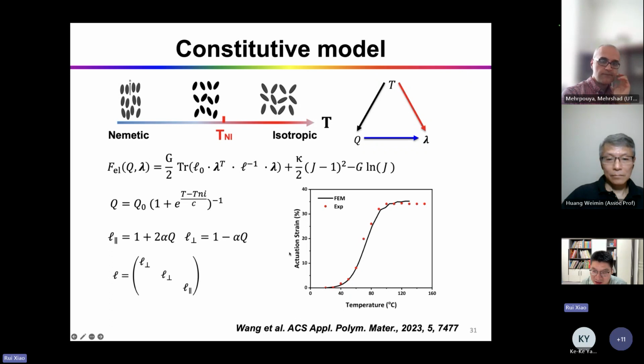Basically, at high temperature it's random direction, at low temperature you have orientation. We fix the strain, and from that we can get the parameters.